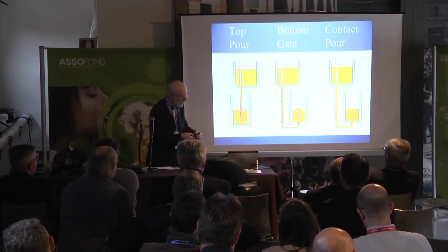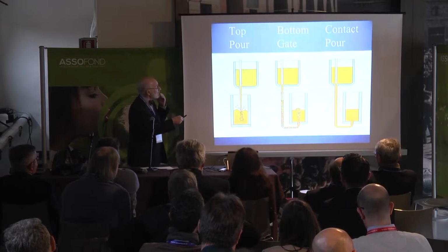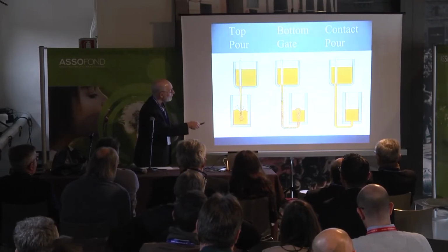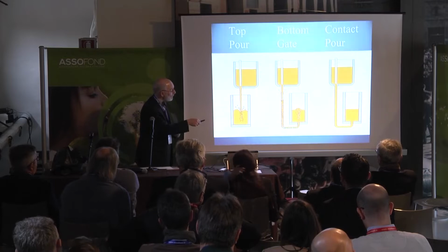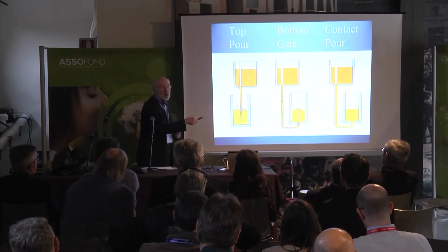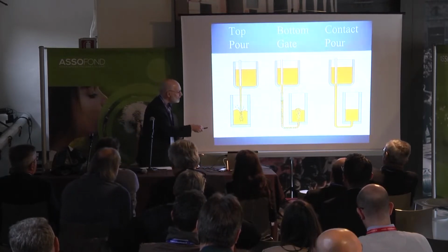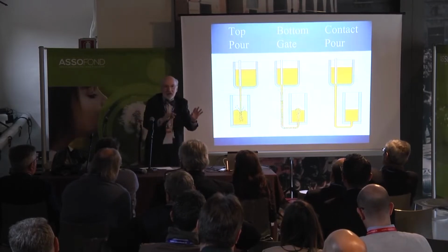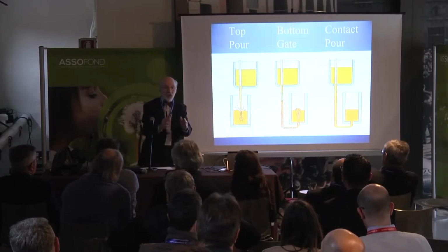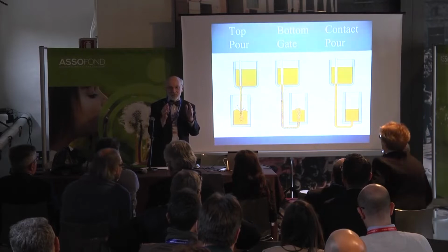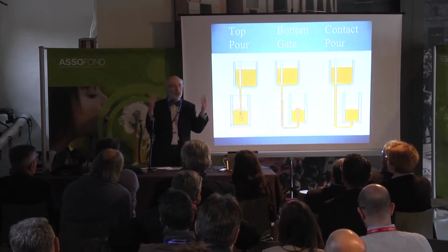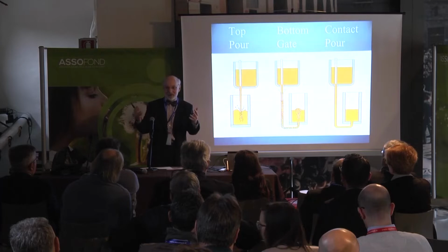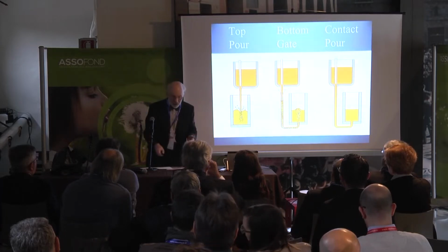Okay. Thank you. You see, most of our casting systems, direct pour, or even bottom gating, because of that cone, we're taking in air into the system. And huge quantities of air, masses of air, are going down into our running systems. There's more air than metal. So it's not surprising we have porosity in the castings. The castings are full of air, plus oxides.